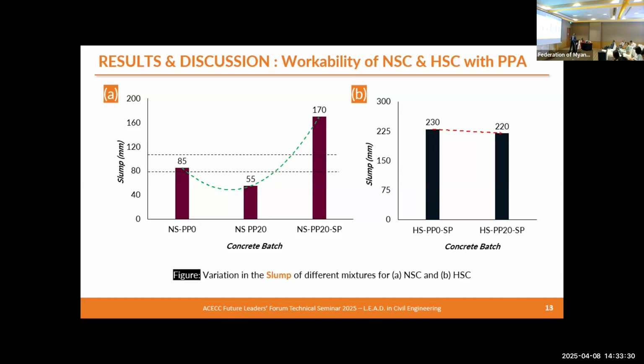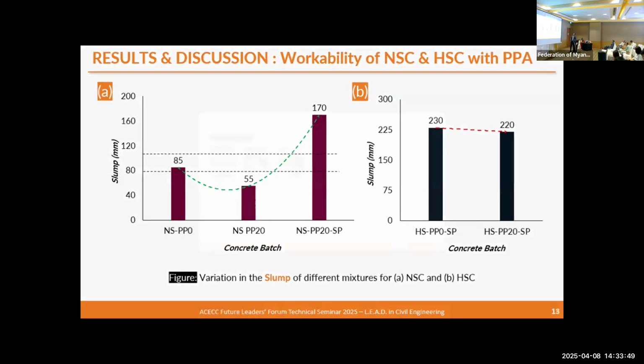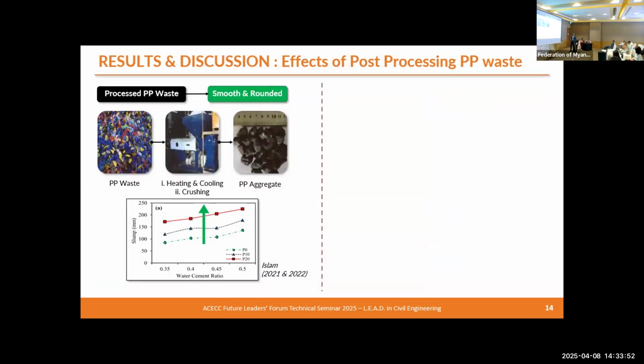Since we need to take it to the range that we need, like the 75 to 100 millimeter range, we incorporated the superplasticizer, but it drastically increased the workability. So we need some future studies on why this drastic increase is happening. We should study it further. In the past literature, there were some doubts among a few researchers whether the incorporation of plastic waste increases or decreases the workability.